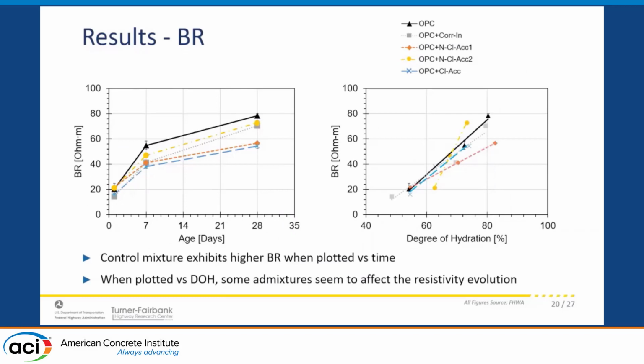So this is the bulk resistivity measurements. We can see the control is always higher than the rest, although we saw before that maybe pore solution is not exactly the reason why the control is higher, because the effect of pore solution varies over time.